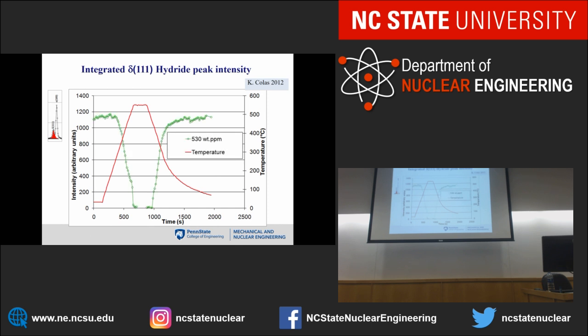So this is what the diffracted intensity looks like at the beginning. No change, no change, no change, no change. I start to dissolve. It's all dissolved here. Right? I keep on going. I'm increasing in temperature, have that flat top there, and then I start cooling, and then I start at this temperature, at this time here, I go whoop, and that's the precipitation again. If I now raise the temperatures, this temperature here is the dissolution temperature, and this is the precipitation temperature, right?